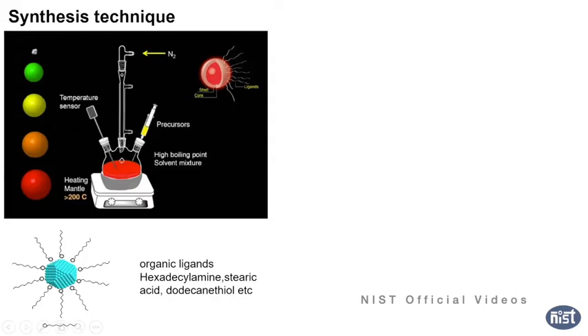So how it works: it forms crystals, and some organic ligands attach to the surface of the nanocrystals. The ligands are different kinds of amines and acids, and they should have a long carbon chain. Due to this long carbon chain, it disperses in non-polar solvents like hexane, toluene, chloroform, and so on. Of course, you can transfer to a polar solvent, but then you need to change the ligand again after formation of the nanocrystal. Generally we use a high-boiling non-polar solvent, because a polar solvent like water or ethylene glycol reacts with the nanocrystal ions and destroys the growth of the nanocrystal. That's why we use the non-polar solvent, and it works very well.